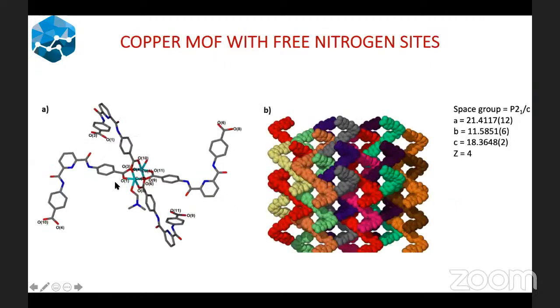We realized that the MOF is made up of a copper paddle wheel secondary building unit. We have a coordinated DMF molecule, which is coordinated to the copper. And of course, the water, which is represented by this oxygen atom, is also coordinated. And you can see some pores here, but they are very tiny. This diagram includes the coordinated water and DMF molecule. Those can be removed to provide the active sites, which can enhance adsorption of carbon dioxide and other gases. So in this case, we were successful in isolating the MOF using the pincer ligand.